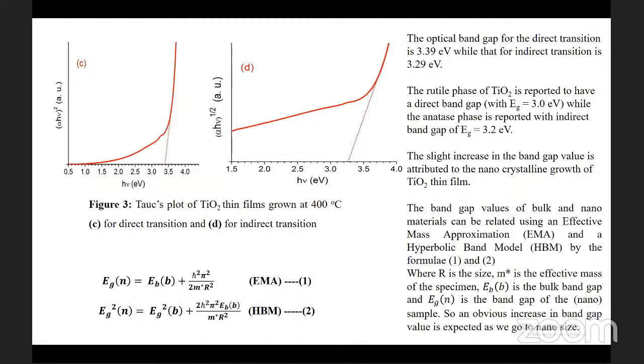This slide shows the Tauc plot of TiO2 thin films grown at 400 degrees centigrade. Figure 3C shows the direct transition and D shows the indirect transition. The optical band gap for the direct transition is 3.39 electron volts, while that of the indirect transition is 3.29 electron volts. The rutile phase of TiO2 is reported to have a direct band gap of about 3 electron volts, while the anatase phase is reported with an indirect band gap of about 3.2 electron volts. The slight increase in the band gap value is attributed to the nanocrystalline growth of TiO2.